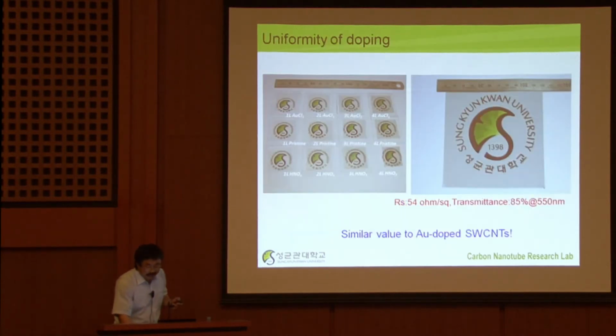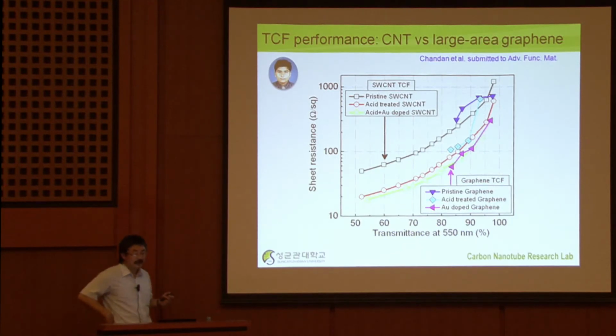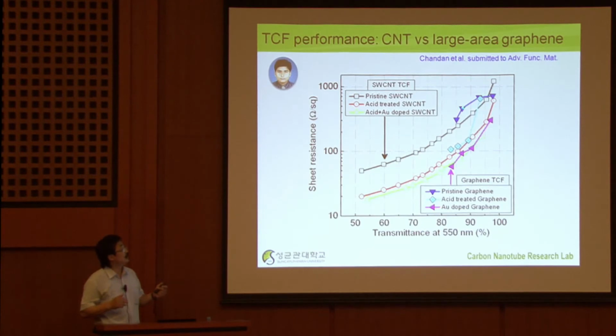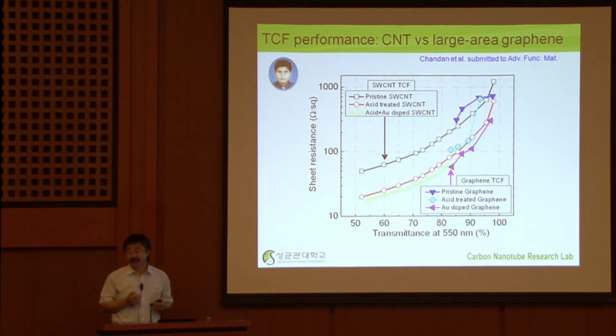So if you combine them together, you can see this is originally single carbon nanotubes, and we have this nitric acid treatment, and we have this gold chloride treatment, and then we have this single layer, double layer, triple layer, quadruple layer graphene, and we again doping. So you see the sheet resistance is reduced almost to a similar level to the best carbon nanotube case. So this way we believe, okay, in terms of this performance, fine.